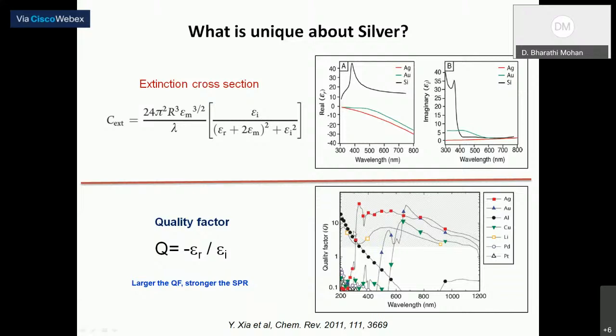Whereas for aluminum, it is high only in the UV region. Therefore, aluminum can be used for UV-based sensors. And if you take gold and copper, these materials can be used, and they will work best in the range from 600 nanometers to 1200 nanometers. So compared to all materials, silver offers very good properties for the nanoplasmonics effect.